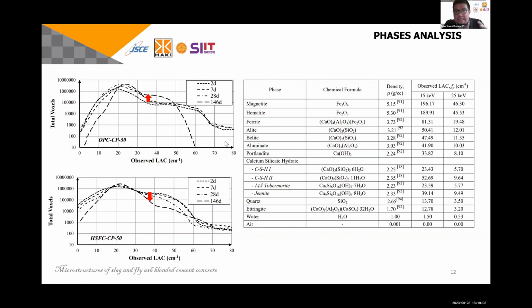The growth of, for example, CH, increasing in CSH, reduction in CH, and then different types of CSH. Here we can find two types in this research. We found two types of CSH, type 1 and also type 2, based on LAC. And also you can see here the change in the volume of the CH in the OPC sample, and also in the fly ash sample.